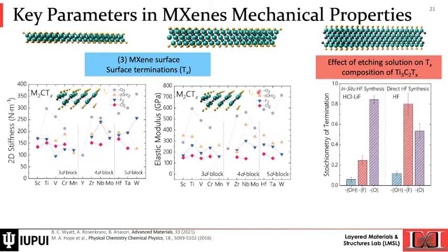I did not include the relatively new study that comes from Professor Talapin's group at the University of Chicago, that showed that you can even have uniform surface termination of MXene. I'm talking about the regular MXene that has been synthesized almost everywhere around the world, using the MAX phase precursor and putting it into aqueous hydrofluoric or fluoride containing solutions. So by playing with the concentration or etching solution type, we can tune these, and that will significantly change, look at the variation here, the mechanical properties, the elastic modulus of the resulting MXene.